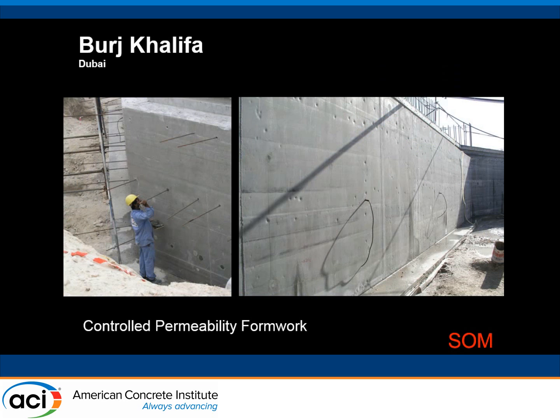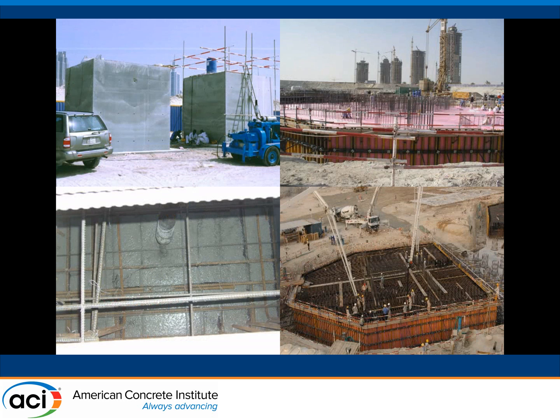These are actually images of the real mat foundation where we used controlled permeability formwork, which in combination with the microsilica and the low water cement ratio really minimize the permeability of the surfaces of this concrete. So it's this really high quality, low permeability mix to cut down on the amount of intrusion of corrosive elements.